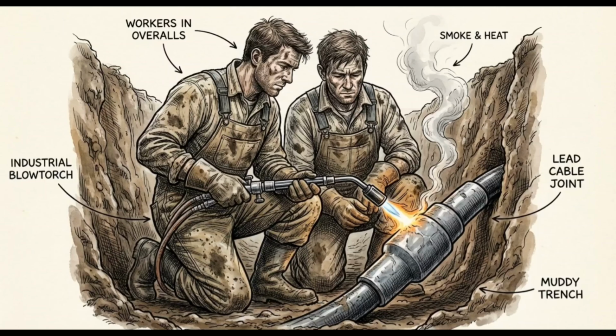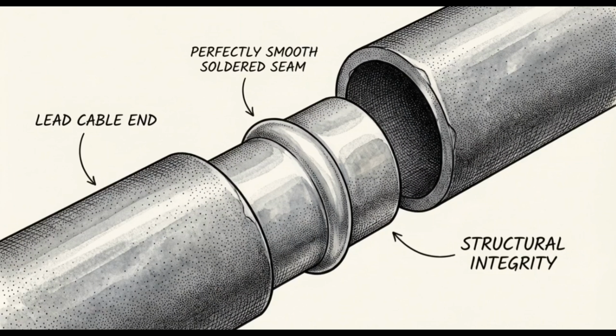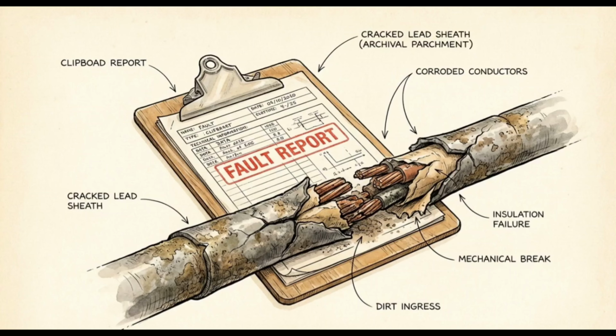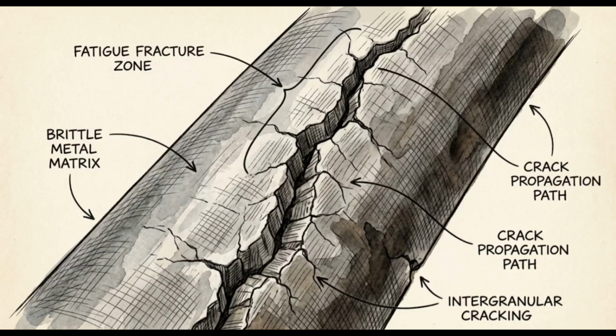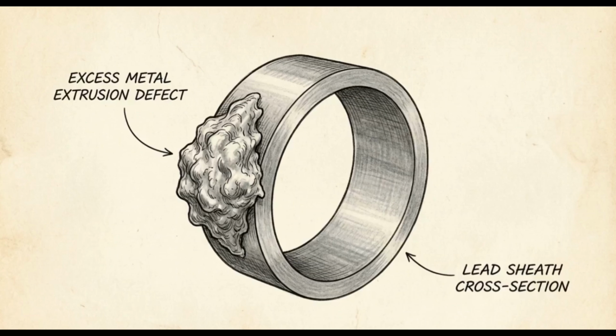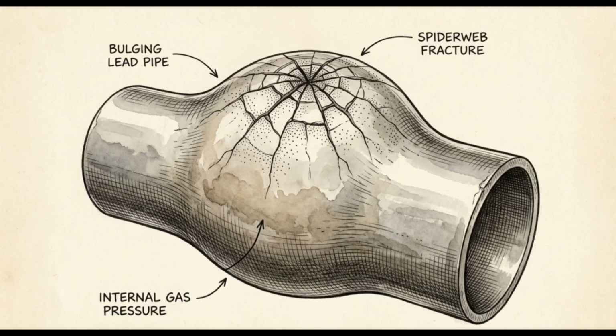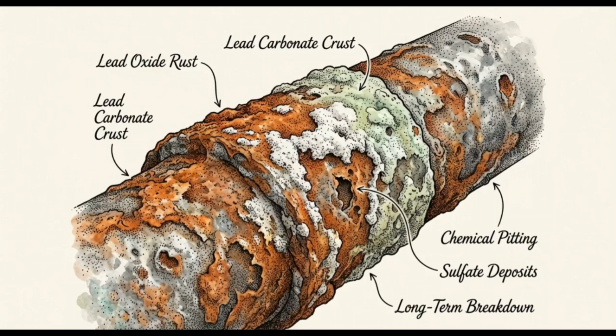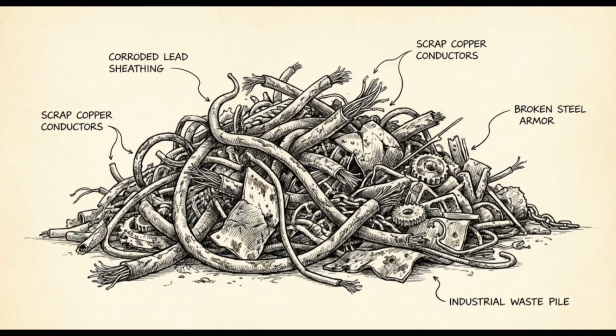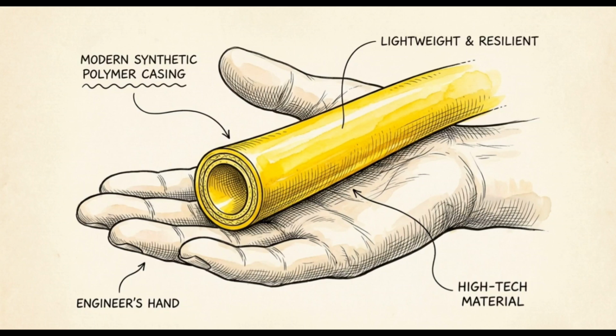Furthermore, successfully splicing and sealing these heavy lines in the field demanded highly specialized plumbing skills to ensure the joints were perfectly sealed without damaging the internal paper insulation. Over decades of use, large utility operators consistently ran into four main fault categories with lead: fatigue cracking from physical movement, manufacturing extrusion defects, fractures caused by internal gas pressure, and long-term chemical corrosion. While lead survived for generations, its inherent weight and structural vulnerabilities eventually forced engineers to transition to the lighter, more resilient synthetic polymer sheaths used today.